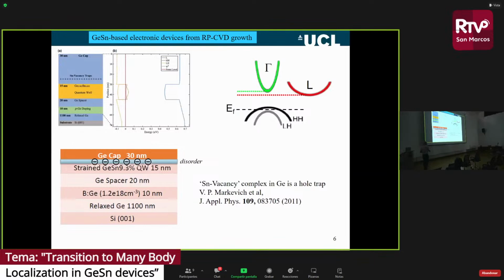That's that. And then this is the introduction to the germanium tin devices. They're grown by reduced pressure CVD. We collaborate with the University of Warwick, which is quite near the city of Birmingham in England. They are grown on silicon, so the basic substrate is silicon. And then they grow germanium layers, they put doping in, they put spacers. The germanium tin itself is confined to just 15 nanometers of the quantum well. So when we put tin in, that reduces the band gap. This forms a quantum well, and then we cap the layer.